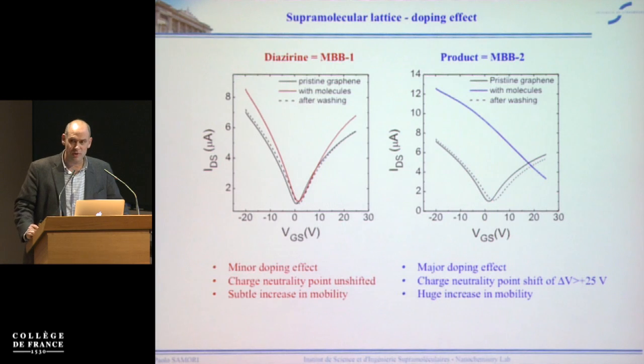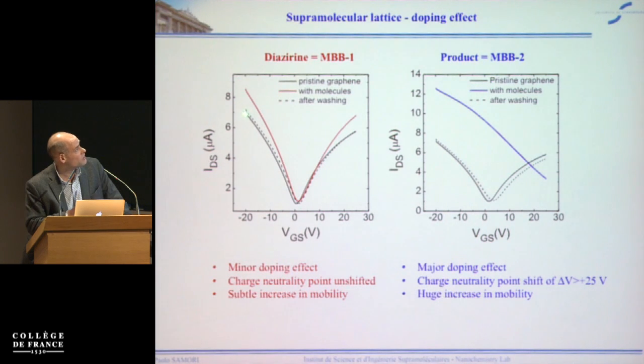And now at this point, we can make a real device. We can look at the IV characteristic of our monolayer CVD graphene. So we start from this curve here. There's a curve in black. And you can see that we have a neutrality point that is located at 0. When we adsorb the diazirine molecule, there is a minor shift, so a minor doping, a minor shift of the neutrality point here in red. And actually, there is a subtle increase of mobility.